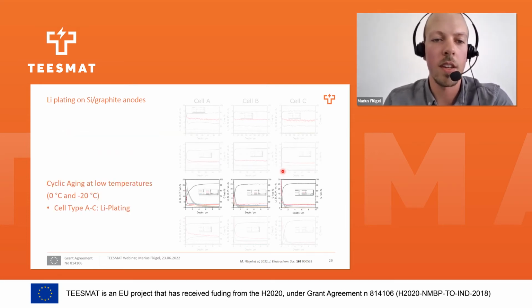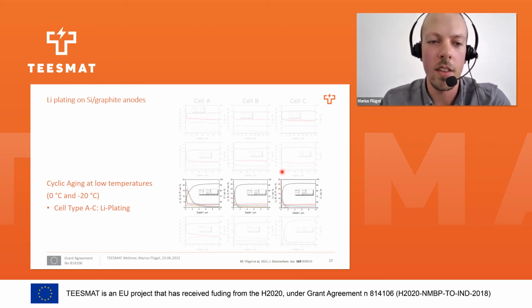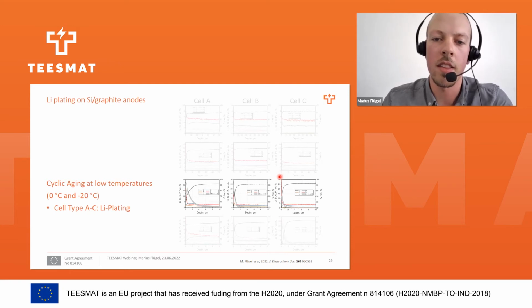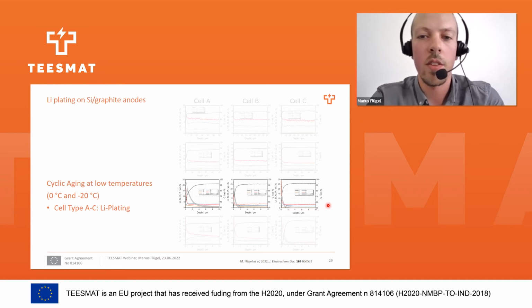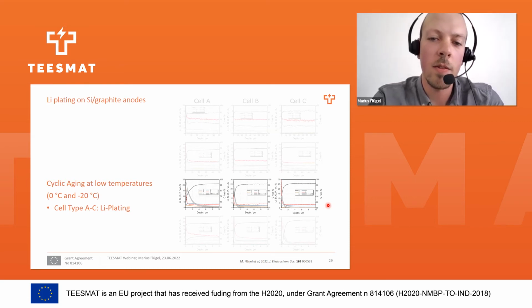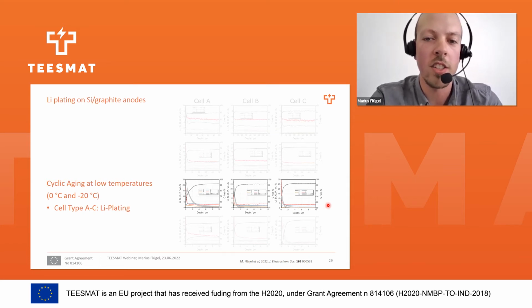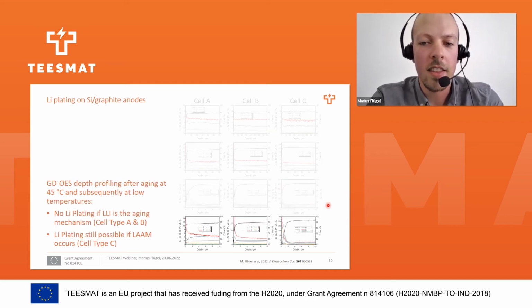However, if we cycle them at low temperatures, 0 degrees Celsius for cell type B and C, and minus 20 degrees Celsius for cell type A, we saw lithium plating, which could be quantified with our recently developed method. What we did then was we took a separate set of cells, first cycled them at 45 degrees Celsius until we reached an SOH of 80%, and then we cycled them at 0 degrees or minus 20 degrees. So we combined both aging procedures and wanted to know if lithium plating is still possible.